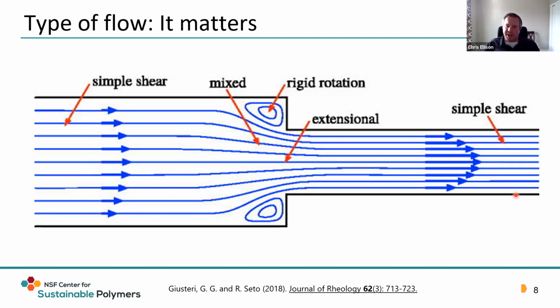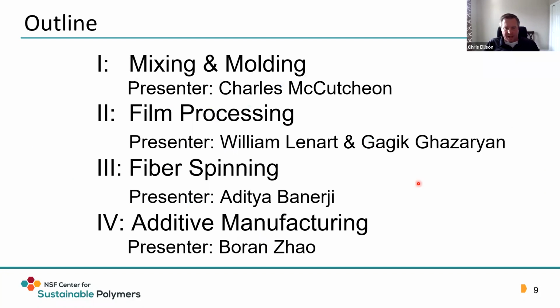This shows the streamlines of the fluid, a polymer melt, let's say, and the size of the arrows indicates the velocity of the flow. Essentially you have a large tube going to a small tube. Where this contraction happens, there's a significant amount of extensional flow or mixed shear and extensional flow. Whereas at both ends of this picture, you typically just have simple shear and roughly parabolic velocity profiles. So this is a very simple flow, but it has a very complicated type of shear rate and type of deformation.